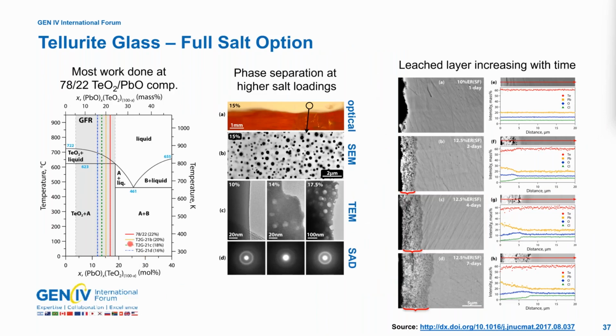Looking at the lead tellurite system, this is the binary phase diagram. We've got the glass forming region in gray. All of our work pretty much is focused on this red line, or the 78 mass percent TeO2, 22 mass percent PbO. We did look at these other lines to see if we moved closer to the middle of the GFR, if these glasses would behave better, and they tend to crystallize a lot more, and the durabilities just weren't as good. So I feel like a lot more work could be done to optimize these particular glasses if waste forms were to be made.